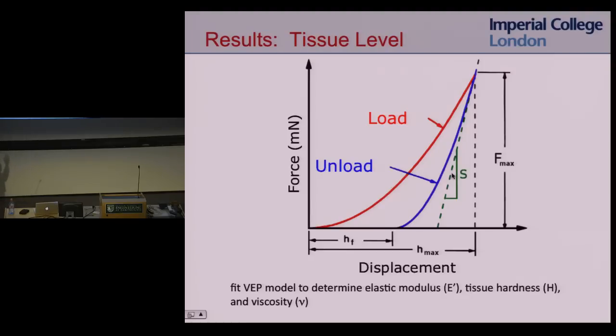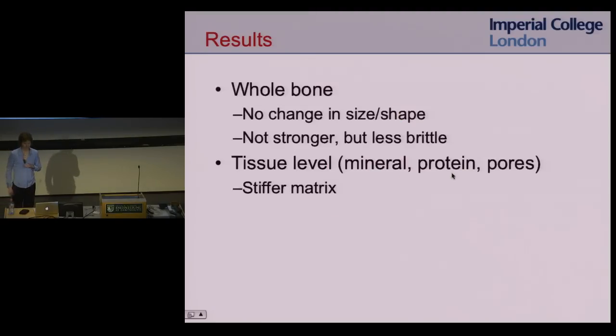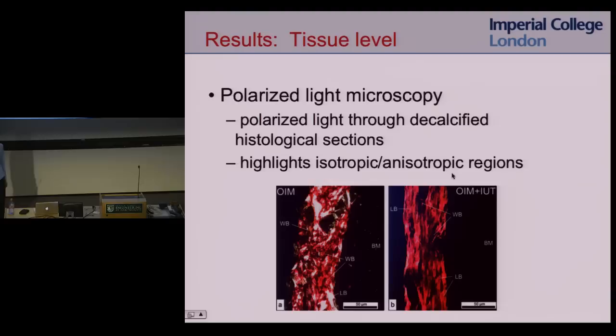So again, load deflection, your force displacement, very similar to three-point bending. But now the interesting part of the curve is the unloading part. So you're recording both the loading and the unloading part, and you're getting most of the data from the unloading part of the curve. And so then we can fit the viscoelastic plastic model to this curve in order to calculate elastic modulus at the tissue level, tissue hardness, and viscosity. And what we found is that the stem cell treated bones had a stiffer matrix. So something about the mineral makes it a stiffer matrix in the stem cell treated bones.